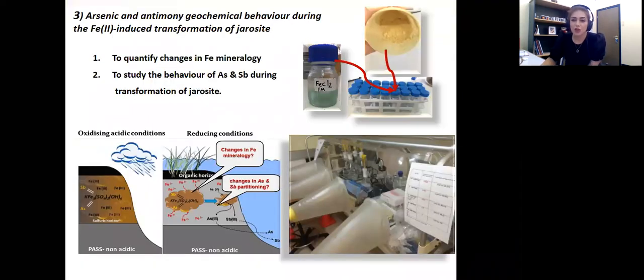So as I mentioned, I synthesized my jarosite inside the laboratory following the protocols that are available. And I co-precipitated arsenic 5 and antimony 5 inside the structure of my synthetic jarosite. And I conducted this experiment under completely reducing conditions. So again, I used the anaerobic chamber to put my samples there and to start the experiment.